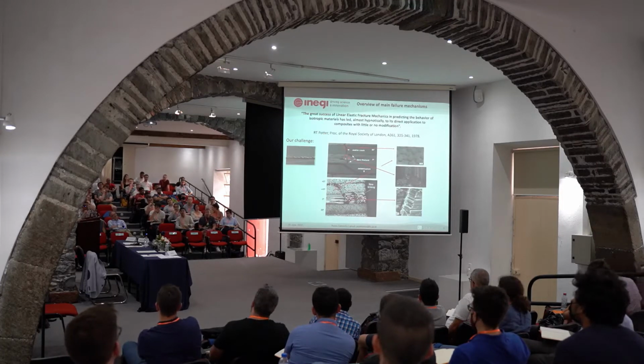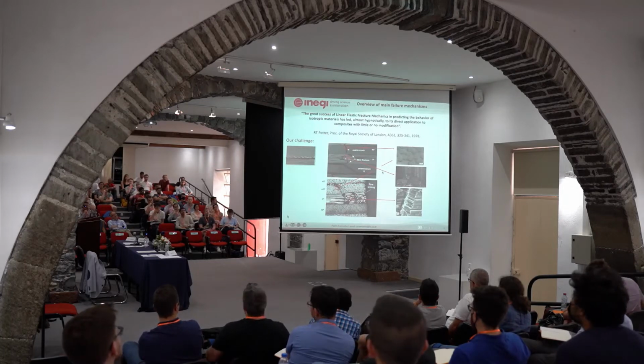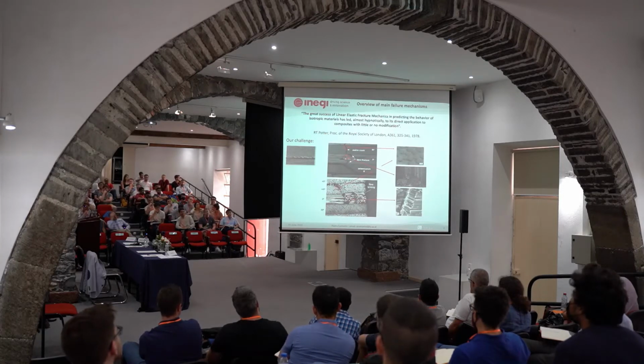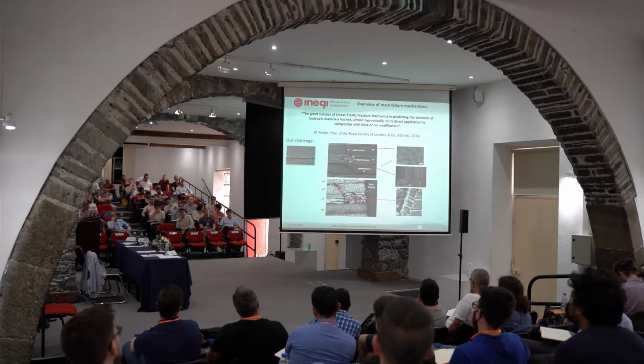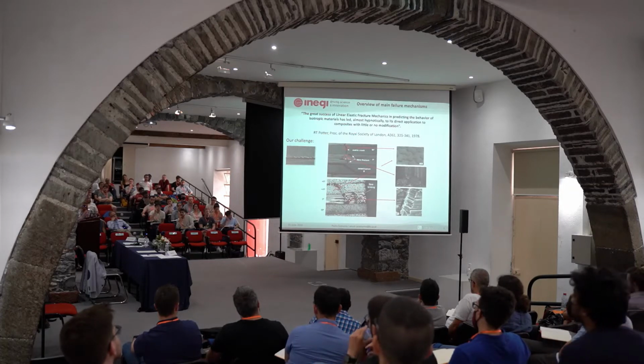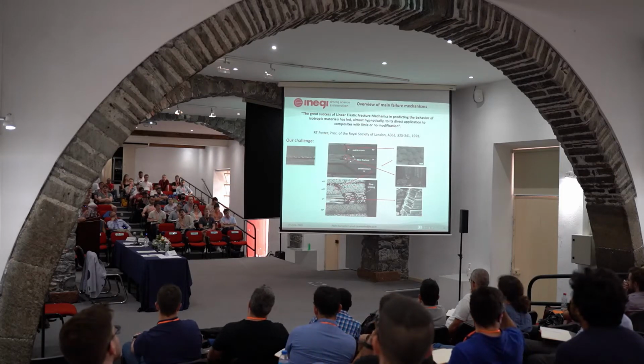So, and our challenge is really to develop physical models and then computational implementations, if necessary, that represent this. So you can see that you don't often have one main crack like you would in a metallic structure. You have a network of failure mechanisms that have different orientations that interact in a complex way. And this is really challenging in terms of developing models. But I think one of the key aspects is that you need to understand all these details in order to have models that somehow take into account all these observations. And I'll try to show you how we try to do that, at least when we homogenize composite material.